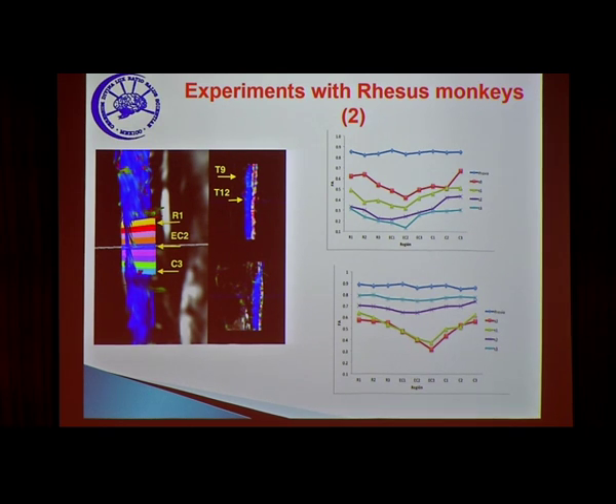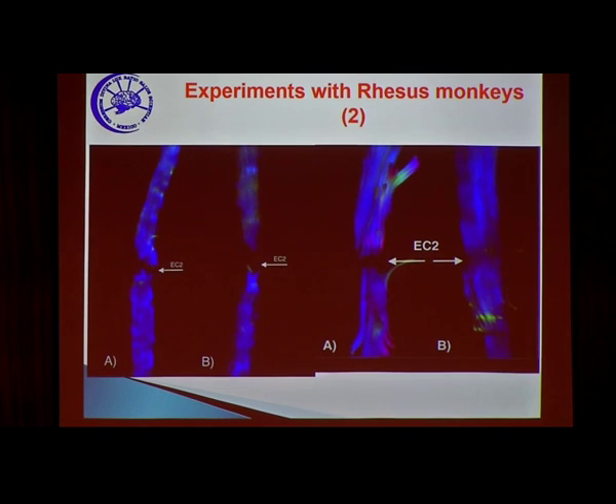But in the case of the monkey implanted with polymer, this is the value before lesion, and then it goes down to this value, but then after 1 week, 1 month and 2 months, the values of this parameter go up, while on the contrary, in the control it went down. So this is the image. The left-hand image is at the moment of the transection. You can see here the cut of the spinal cord.